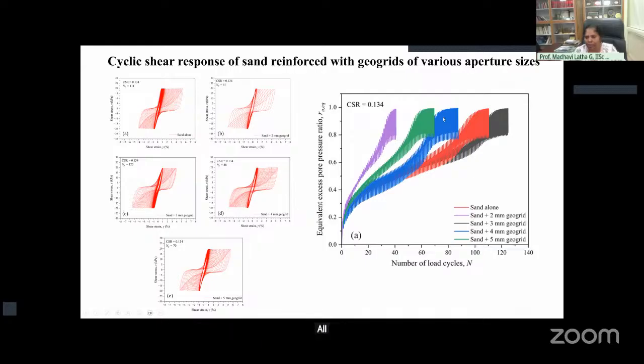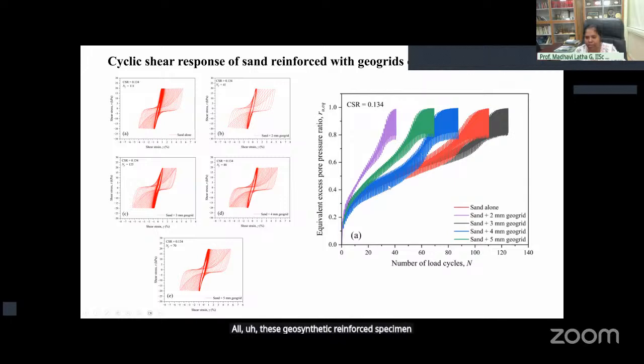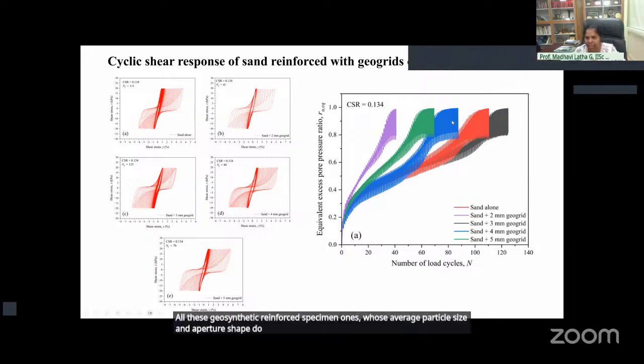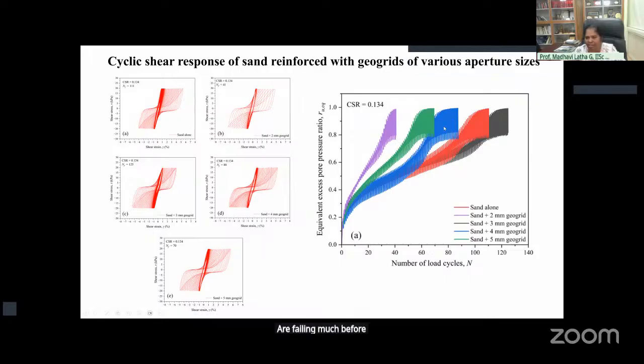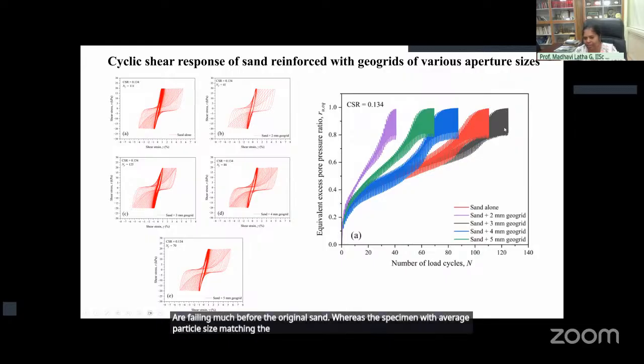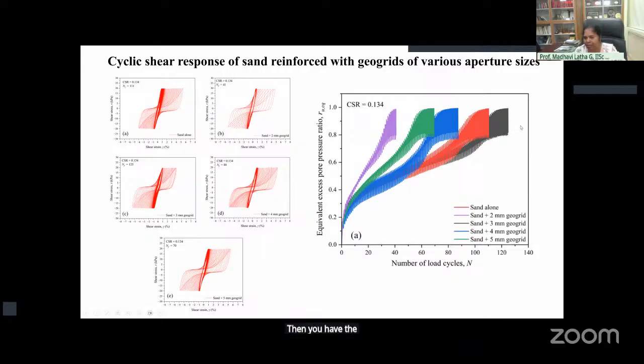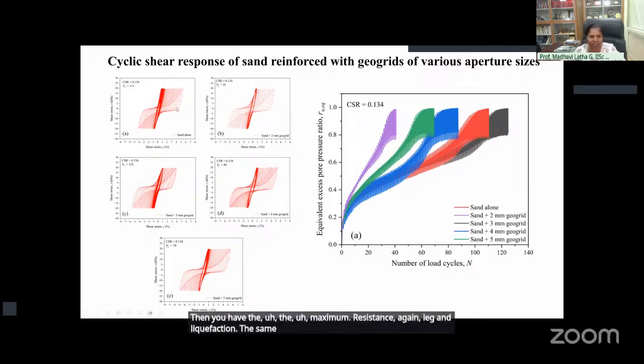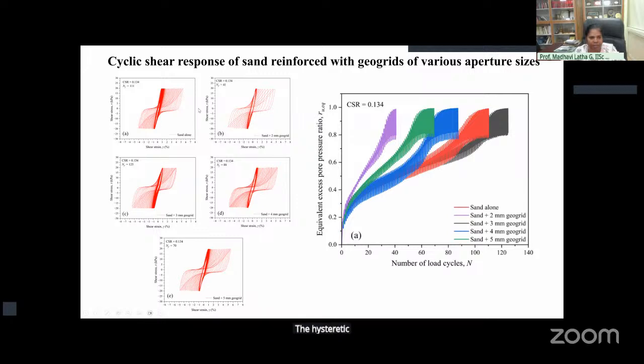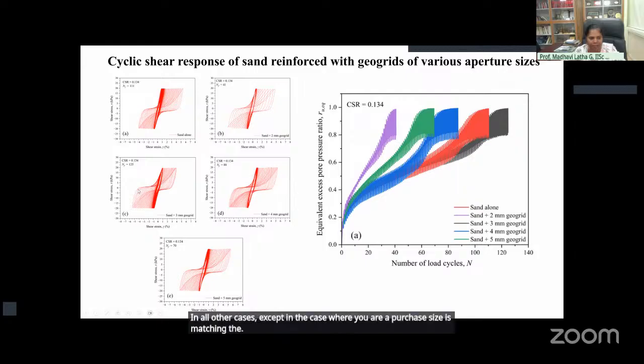All these geosynthetic reinforced specimens whose average particle size and aperture size do not match are failing much before the original sand. Whereas the specimen with average particle size matching the aperture size has the maximum resistance against liquefaction. The same can also be seen with the hysteresis loops, where we are plotting shear stress versus shear strain. The hysteretic behavior clearly shows that the loops widen very quickly in all other cases, except where your aperture size is matching the average particle size.